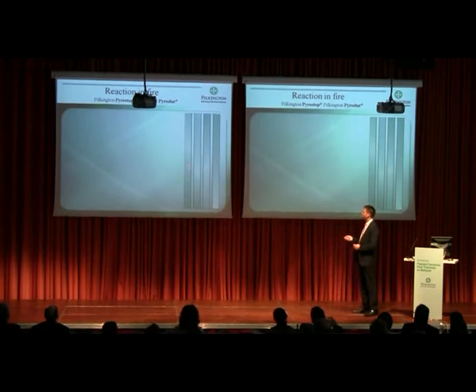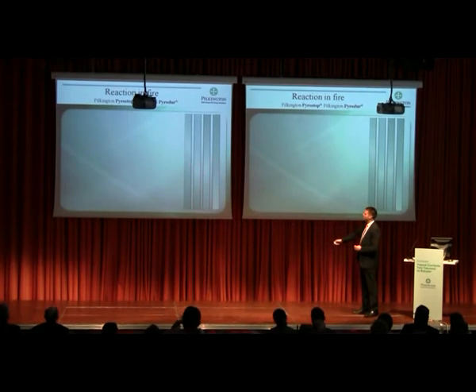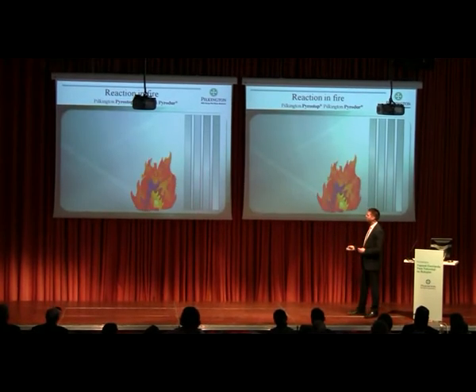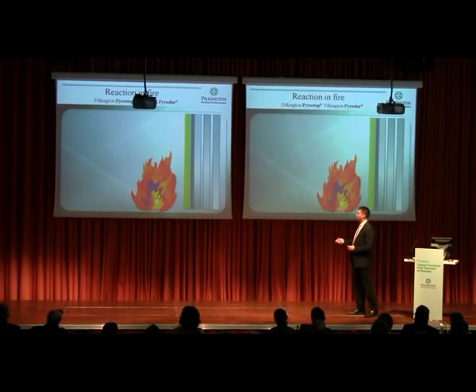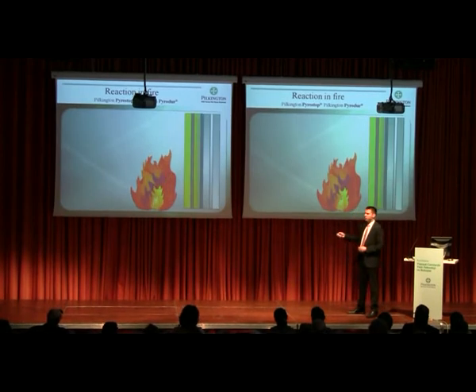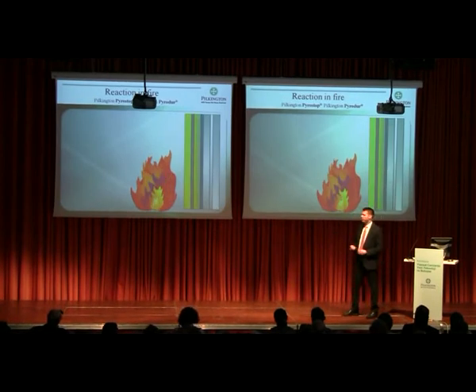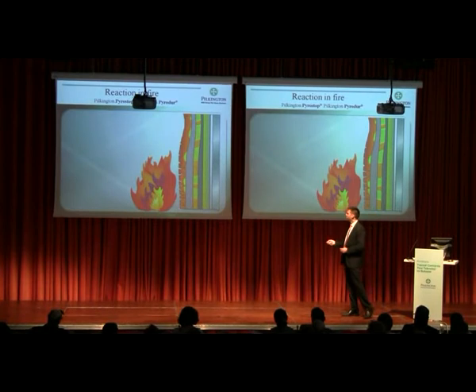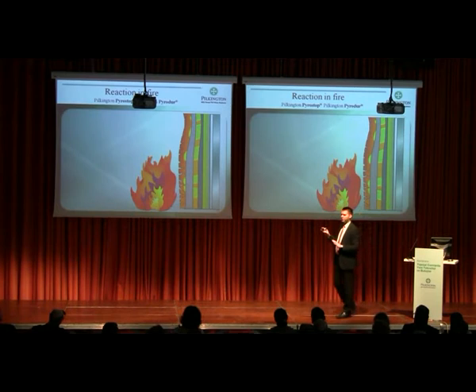So this is how it looks: float glass, interlayer, float glass, interlayer. The fire starts. We have temperatures of 100, 200, 300, 400, up to 1000 degrees in case of fire. The first float glass cracks. The first interlayer is foaming up and building a kind of opaque shield. I will show it to you on the next slide. I have some pictures of that as well.